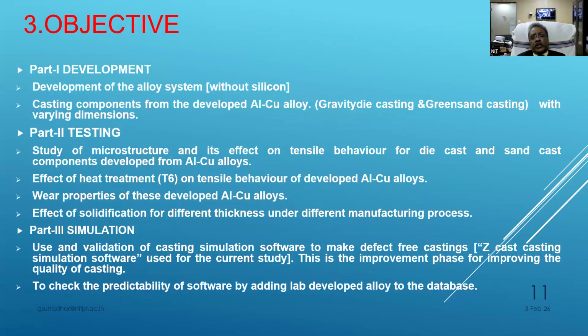So now our basic objective, or this research work, has three parts. The first part is the development of an alloy system, and it should preferably be without silicon. The silicon is only in the wrought aluminum or aluminum copper master alloy. A very trace amount of silicon is already in the master alloy, but we are not adding any silicon to the master alloy. The master alloy is aluminum 50% and copper 50%.